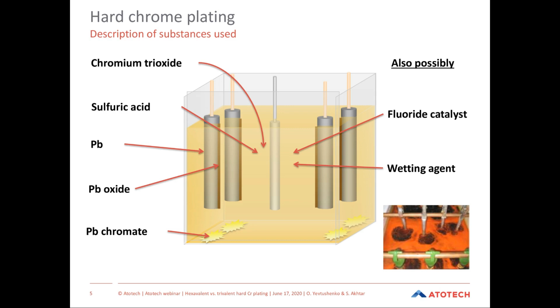Nonetheless, the chemistry to this day is still considered as being one of the most toxic in the industry, which is no surprise when we consider that the current chemical formulations consist of chemicals such as chromic acid, sulfuric acid, lead anodes, lead chromate from the anodes, and fluoride-based catalyst systems. So it's no surprise that the toxic nature of these chemicals attracts attention from the environmentalist groups.